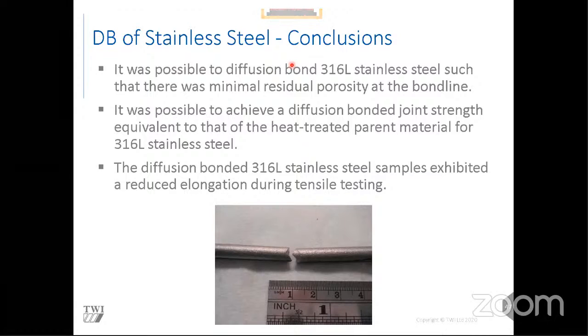Is chromium oxide layer a hindrance to diffusion? We're lucky with stainless steel diffusion bonding - it's performed at a high temperature, above 1000 degrees Celsius, anywhere between 1000 and 1250 depending on the grade. At those temperatures, the oxide layer fully dissolves into your parent material, so we don't have to worry about it. What we do have to worry about though is chromium has a relatively high vapor pressure, so during diffusion bonding we can actually lose chromium from the surface - it will vaporize off and deposit itself somewhere else in the furnace. So you might want to consider diffusion bonding under a partial pressure of gas to lower the vacuum. But chromium oxide is not a problem, generally speaking.